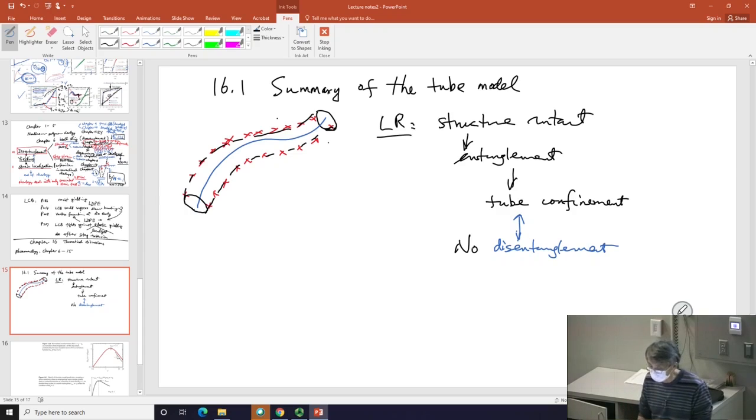that the tube model might be very successful in the linear response region. The tube is simply impossible to disappear, because it's made of all the surrounding chains, and they cannot just disappear all of a sudden in a coherent way. That's why you always have tube constraint, and this enables you to speak about reptation, for example, all the chain dynamics and diffusion issues, in absence of large deformation. So there, of course, there's no disentanglement to speak about.